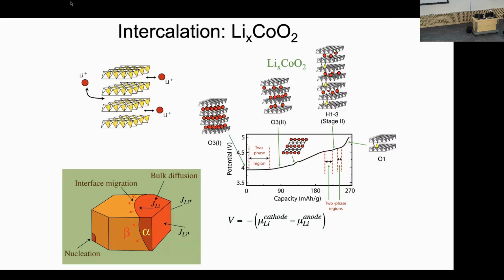And then if you keep pulling out lithium, you get another one of these little kinks. And in this case, it actually stages. So you get, again, ordering, but now along the z-axis. You get a filled layer, an empty layer, filled layer, empty layer, and so forth. So all these things are happening every time you charge and discharge. It's basically going through a binary phase diagram, and a whole sequence of phase transitions are occurring every time you charge and discharge.